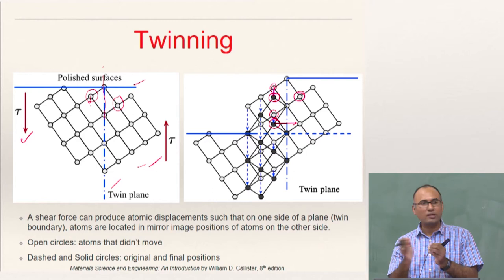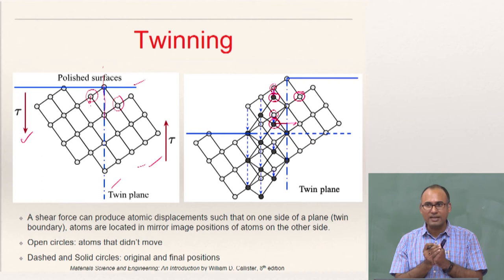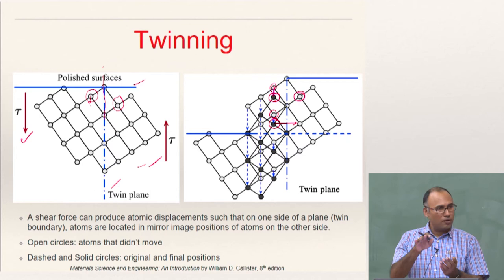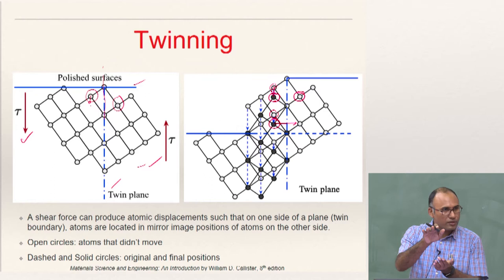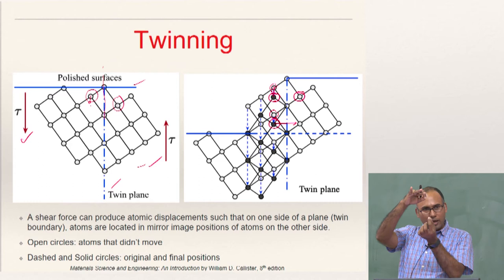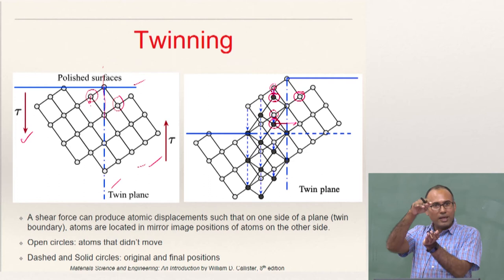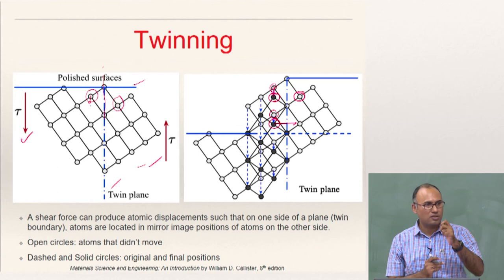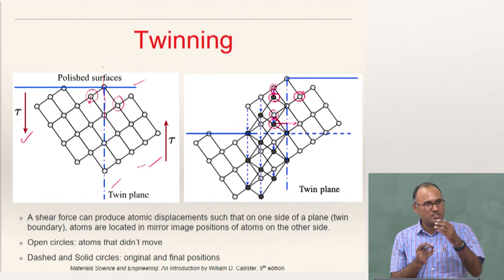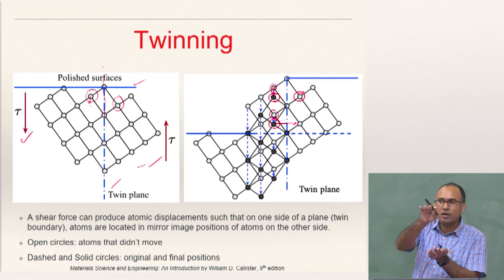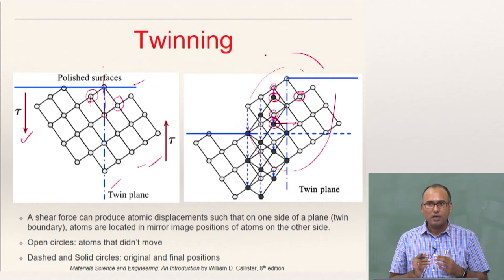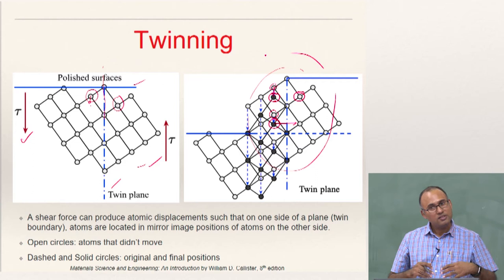If you have a plastic deformation of that kind, such a deformation is called twinning deformation. Like in the case of slip, you can have plastic deformation by glide of a plane of atoms compared to motion of dislocations. Individual atoms break the bond and reestablish the bond. The amount of energy required to cause slip by dislocation motion is much smaller than the amount of energy required to cause slip by glide of a plane of atoms — meaning dislocations help you do slip. Similarly, what we have shown here in a perfect lattice for twinning deformation, dislocations can also help twinning.